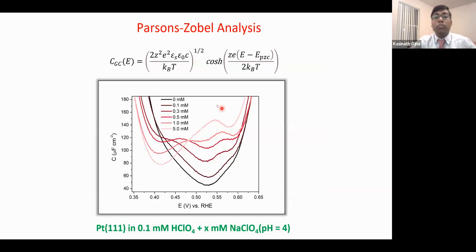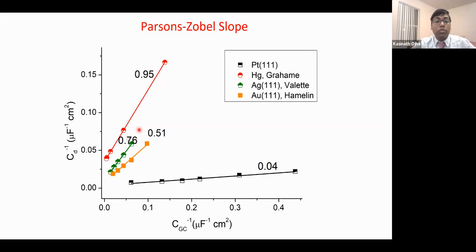Yeah, again, moving forward. If we look at this Gouy-Chapman capacitance, it relates to the square root of the concentration of the ions present in the solution or electrolyte. And I also have the data which have different electrolyte concentrations. So I can look at those capacitance values, and I can also calculate theoretically the capacitance values at those particular concentrations. And I can see how the theoretical value is matching with my experimental data. And that's called a Parsons-Zobel plot. So we plot experimental capacitance inverse versus calculated capacitance inverse.